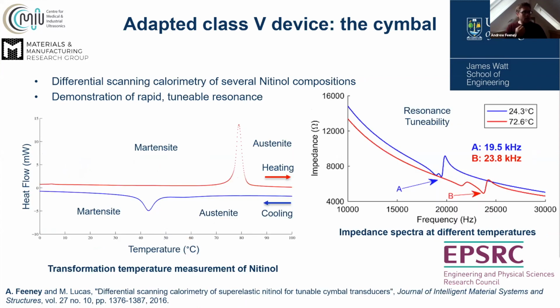So in the work that I've done so far in the fabrication and operation of these devices, I've undertaken various forms of material characterization. One of the most successful so far has been using differential scanning calorimetry. That really is just creating a map of the heat flow against temperature, and using this you can identify where the material will transform. So the DSC result here is shown for nitinol.